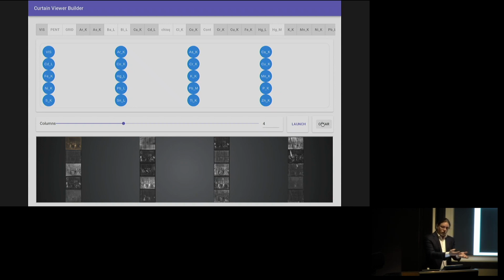the X-rays are absorbed by the electrons in the atoms, those electrons are promoted, leaving unoccupied states in the atom. Other electrons fall down from their higher energy states into those newly available lower energy states, and when they do that, falling down, energy is conserved and they give off X-rays. So the big picture is you put X-rays in, X-rays come out, and you detect the X-rays that come out, because the X-rays that come out have a characteristic energy depending upon the atom from which they have fluoresced.